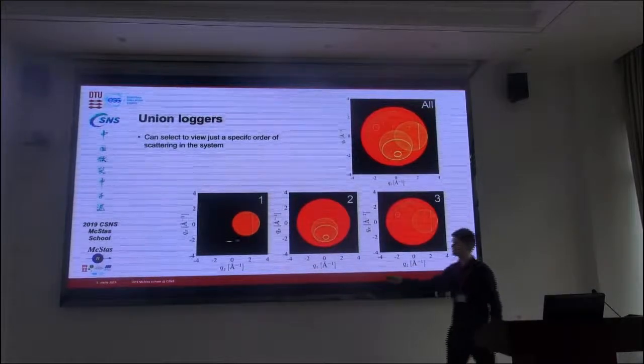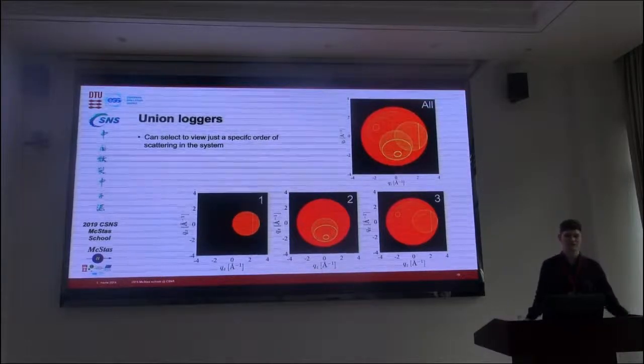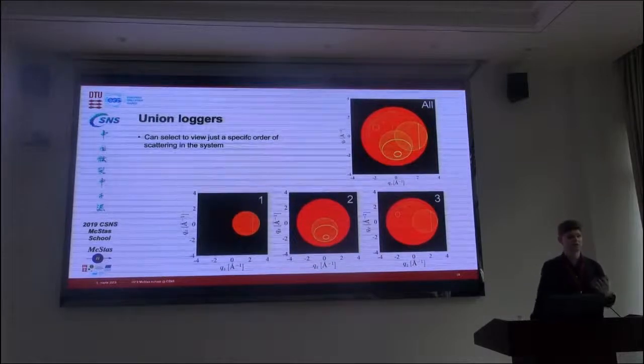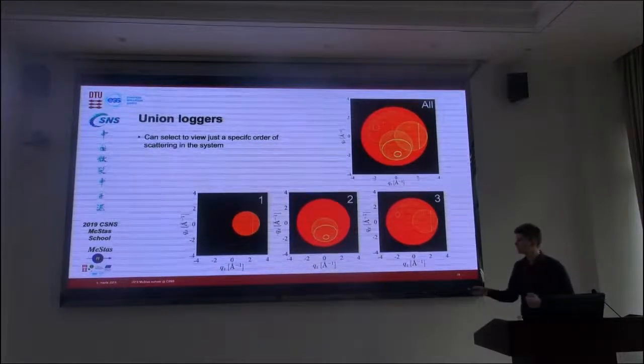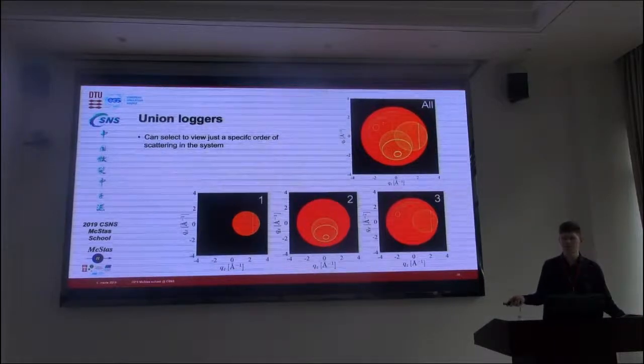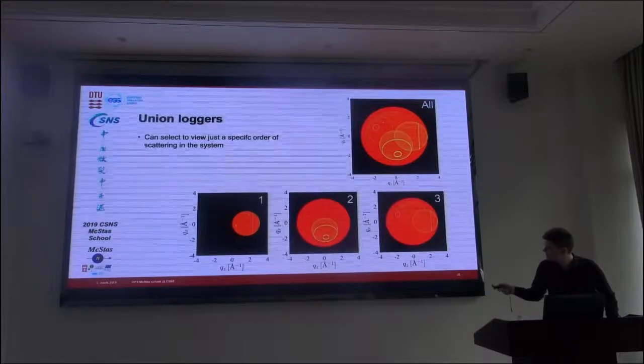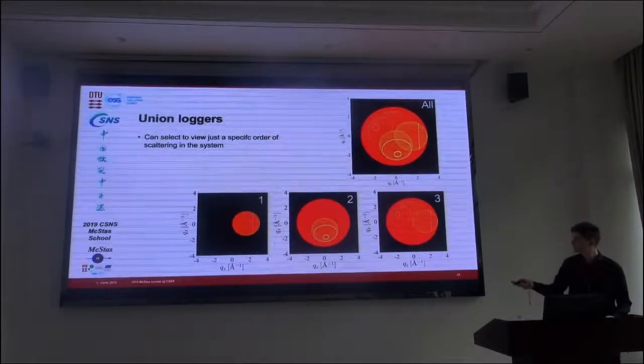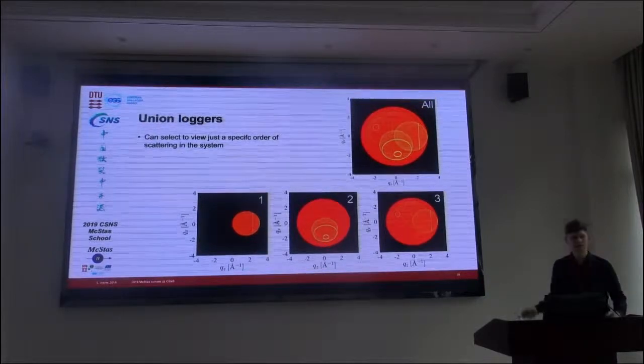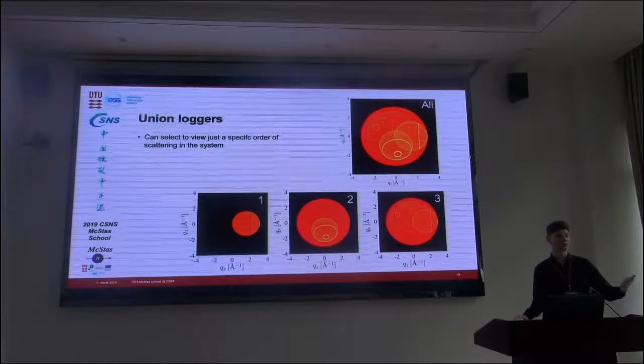Let's split it up into the scattering orders again in order to see what's going on. Of course, here in the first scattering, we knew the initial velocity or the initial wave vector. So we can only reach this part of reciprocal space. Most of it is uniform. That is actually the incoherent scattering. Then there's one little spot. I don't know if it's visible. But that is the Bragg peak. And then there's one line here. And then one little line here. That's the two powder lines that are available in aluminum at this wavelength.